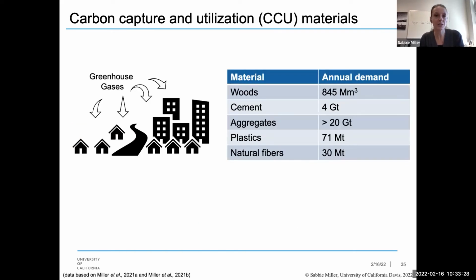The other benefit that we end up seeing associated with our cement and concrete materials is that the really high level of consumption means that there is this potential to convert them into a carbon capture and utilization source. Basically, because we use so much cement and concrete relative to all of our infrastructure materials, if we could re-engineer cement and concrete to act as a carbon sink, this is going to be one of our largest potential carbon sinks in man-made materials that we have on the planet. So this is an active area of research, basically trying to understand which components of our cement and concrete we can use as a carbon capture source, such that we are mineralizing atmospheric carbon dioxide and removing it from the contributors to our climate change.